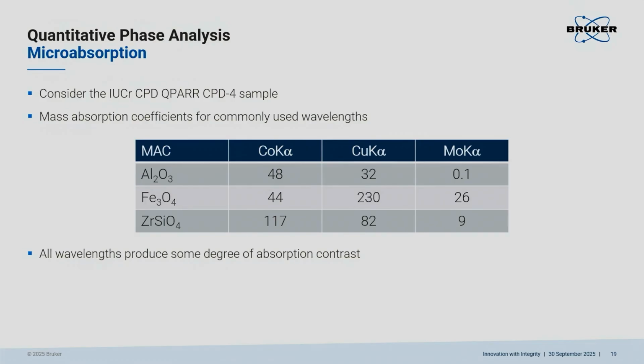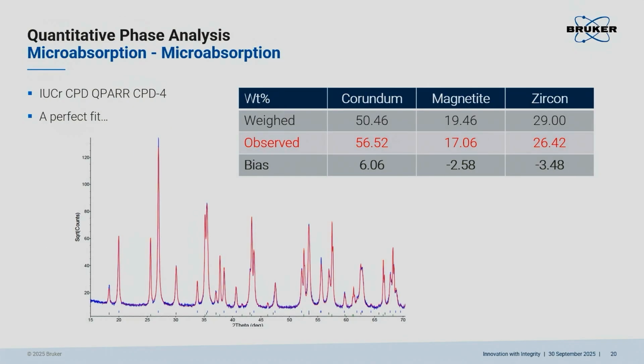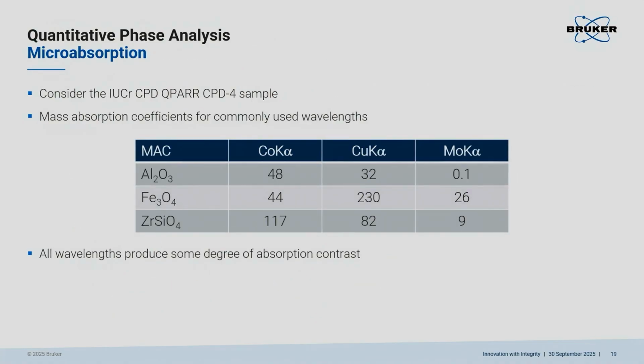Consider the example CPD4 from the IUCr round robin. And again, you have all the information in the paper which I'm going to distribute. Consider the mass absorption coefficients here for the 3 phases: aluminum oxide, iron oxide, and zirconium silicate, for 3 different wavelengths: copper K alpha, cobalt K alpha, and moly K alpha. I'm comparing these because one of the rules of thumb is, if you believe you have a microabsorption problem, or if you know you have a microabsorption problem, change the wavelength. This can help sometimes, but as we can see here, not often.